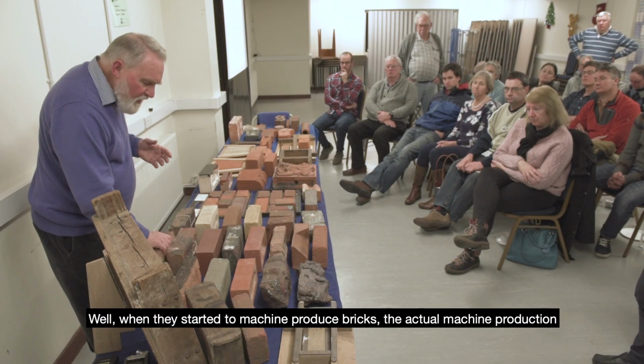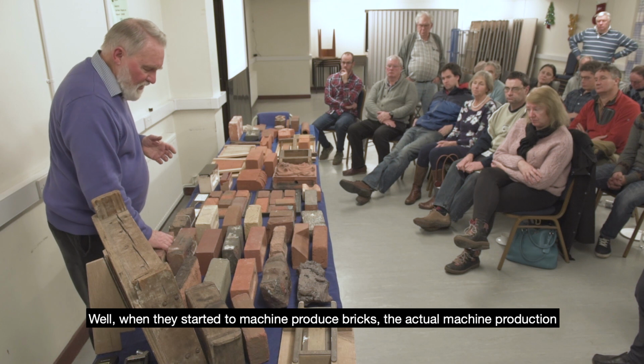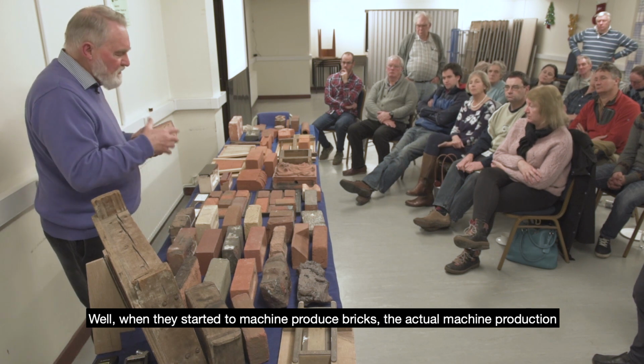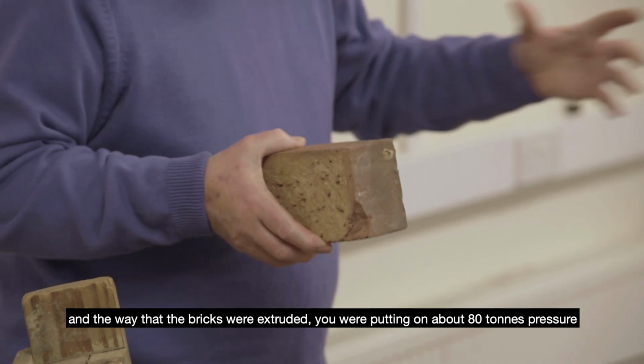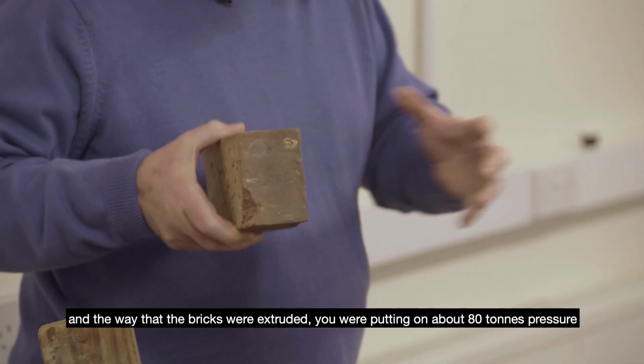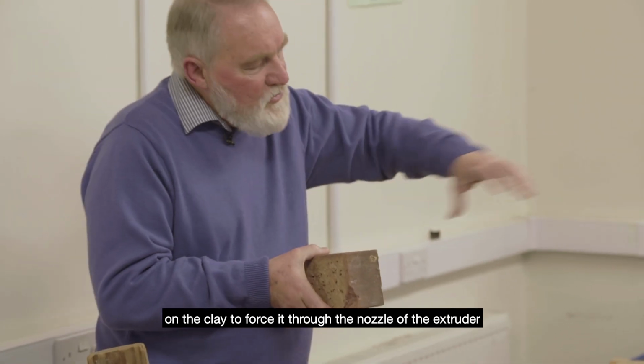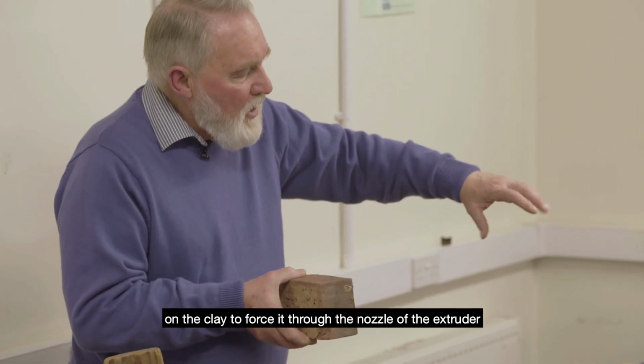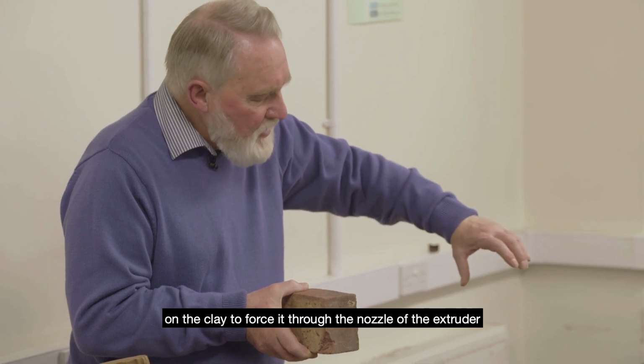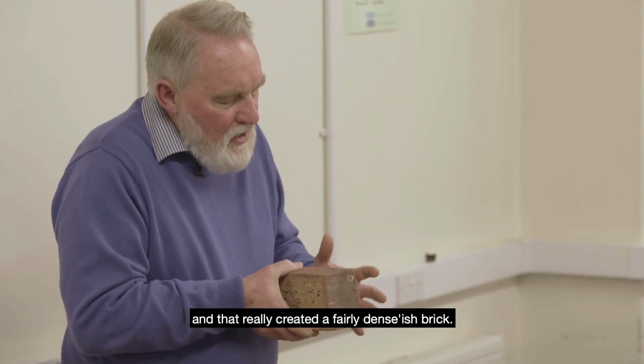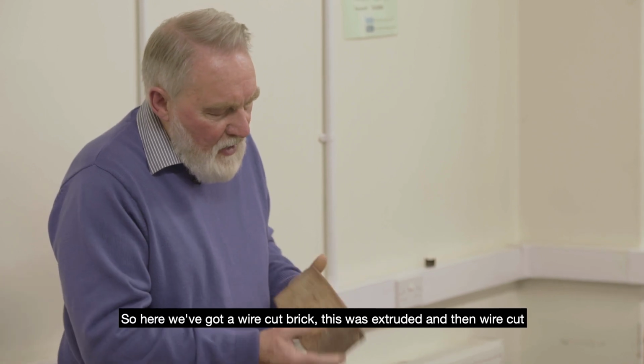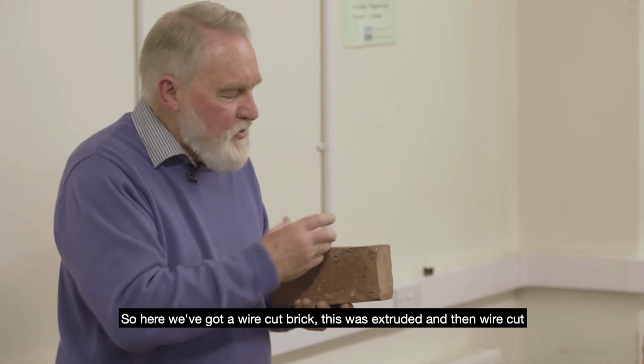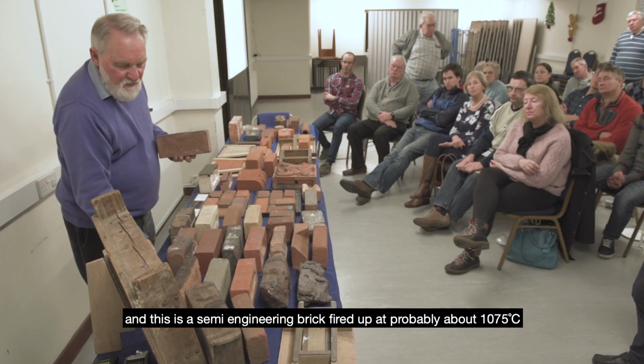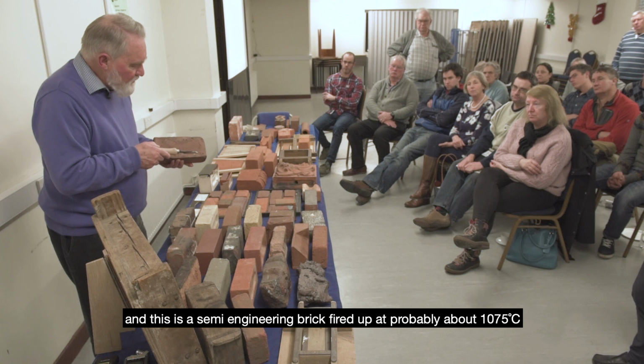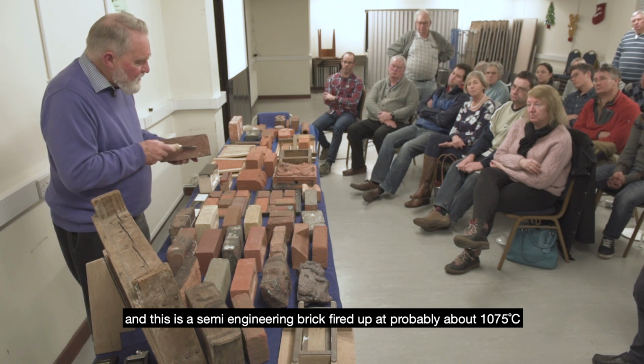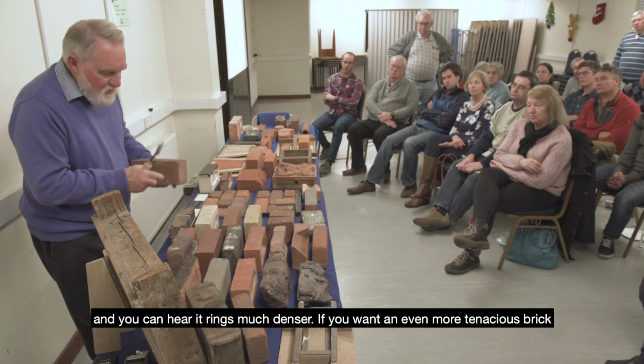Well, how do you produce one of those? When they started to machine produce bricks, the way that the bricks were extruded, you were putting on about 80 tons pressure on the clay to force it through the nozzle of the extruder, and that really created a fairly dense-ish brick. So here we've got a wire cut brick. This was extruded and then wire cut, and this is a semi-engineering brick fired at probably about 1,075 degrees. And you can hear it rings much denser.